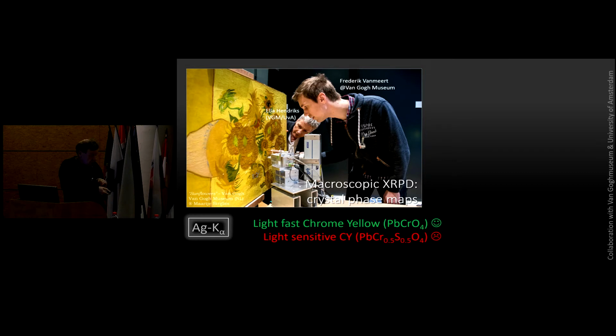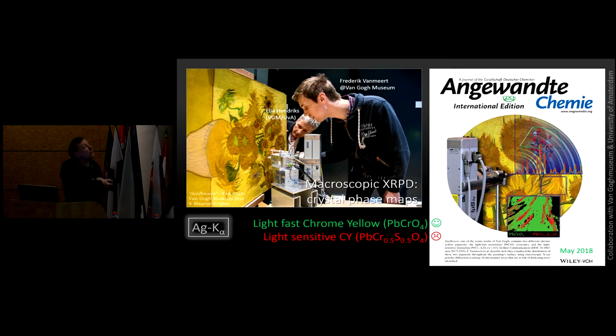So in the chrome yellow world, let's say there is a green one, a safe, light-fast variety. This is normal lead chromate, but there is also a not so safe or a light-sensitive version which contains sulfur. And to see that difference, X-ray diffraction allows you to do that. And therefore, in individual strokes made by Van Gogh to paint these sunflowers, we could map that out. And by knowing where the light-sensitive and the light-fast pigments are, we can more or less tell curators: these parts of the painting, this is where you have to pay attention to, and maybe from these parts we would like to have some samples, please, and not of the rest.